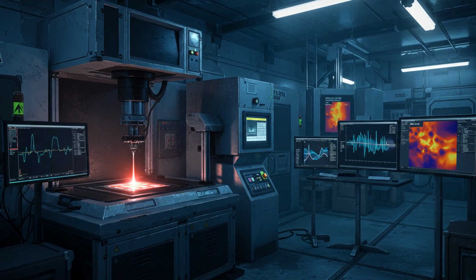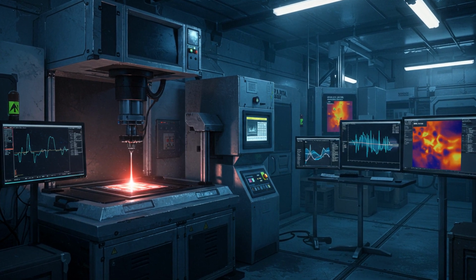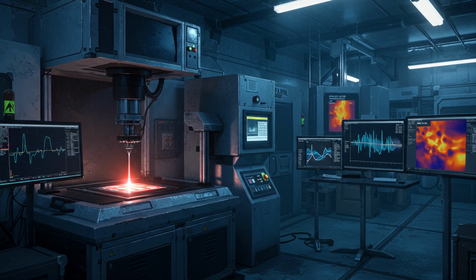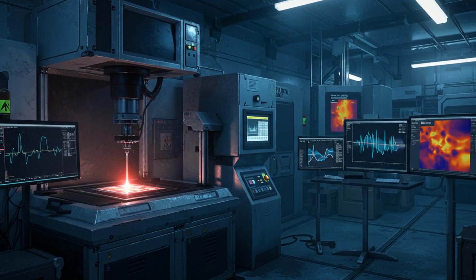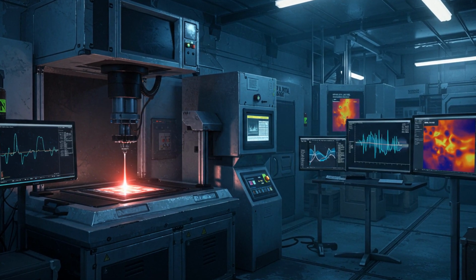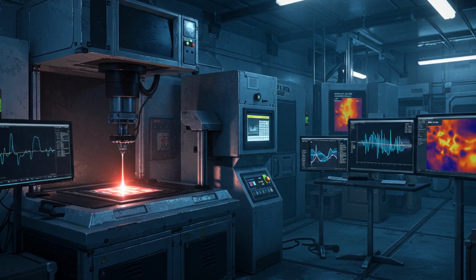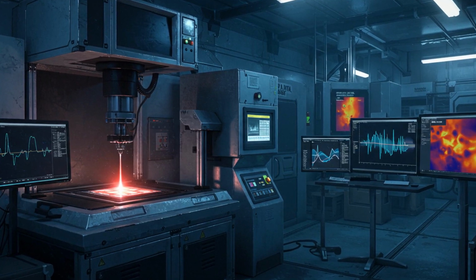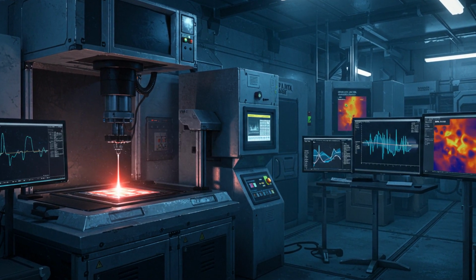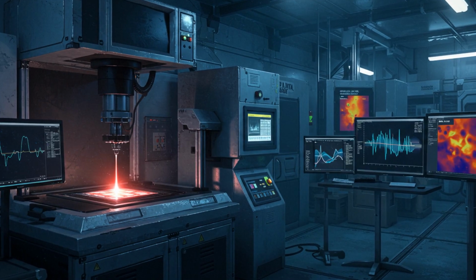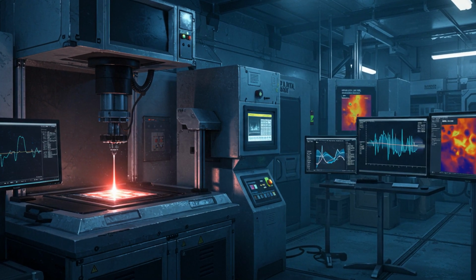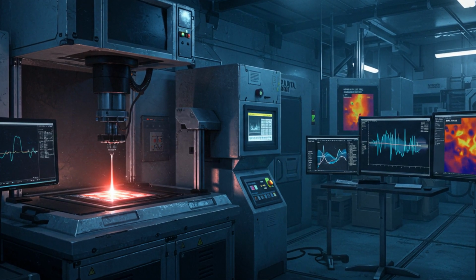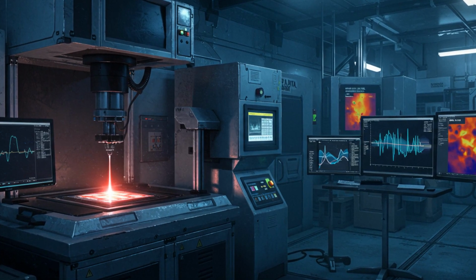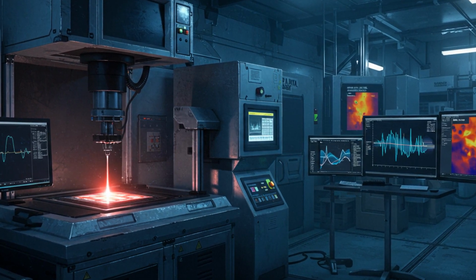After processing, every cell must prove its numbers. Quality control begins with flash testing. A xenon lamp simulates the solar spectrum and delivers 1 sun of intensity, while sensors capture 3 critical values: short circuit current, open circuit voltage, and the maximum power point. From these, technicians compute the fill factor and conversion efficiency. Cells are binned by performance. Those with microcracks, shunts, or low VOC move to lower tiers.